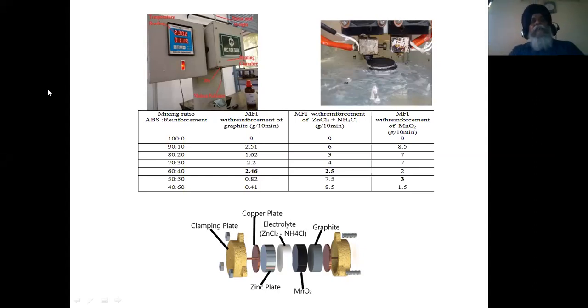So what it actually gives: I put some material over here in granule form. Then I have a control of temperature, and I can put some load on this piston, and finally some wire comes out of this die, and I am measuring how many grams per 10 minutes is the flowability, right? Now you can see this. I selected this ABS as the basic matrix, so ABS as a thermoplastic was selected. Then I put some graphite, zinc chloride and ammonium chloride in powder form, and MnO2 in powder form. So once it was 100% ABS, the MFI was 9 grams per 10 minutes.